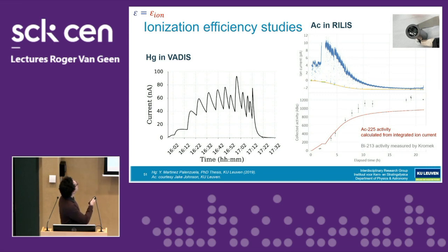So they were trying to keep it under the 80 to 100 nanoamp mark to make sure that they get the best efficiency, not damage that efficiency with too much beam. It was part of a test. You could argue, no, I want more, but then you would have to find a solution on how to recover your efficiency. And you can see here how that measurement was not too bad. It took about an hour and a half.